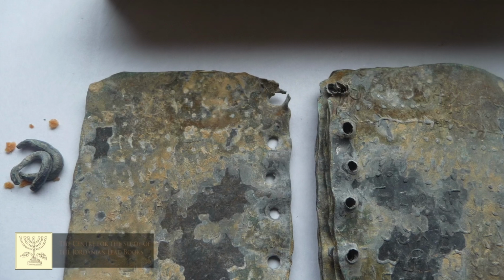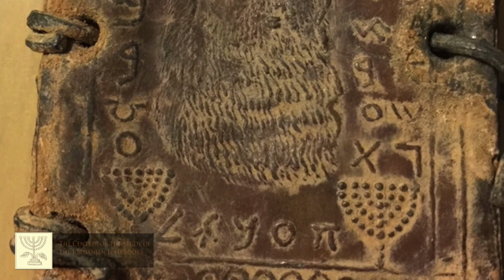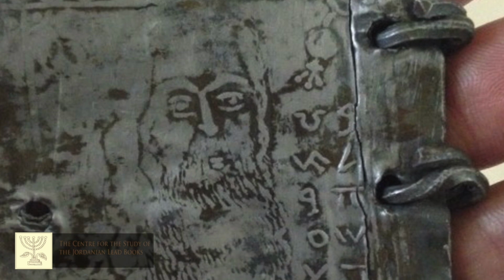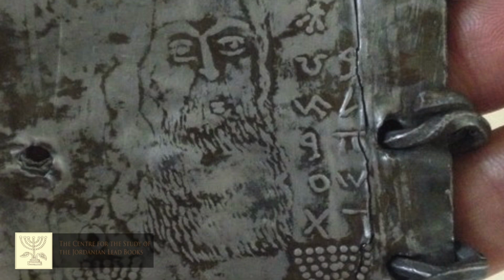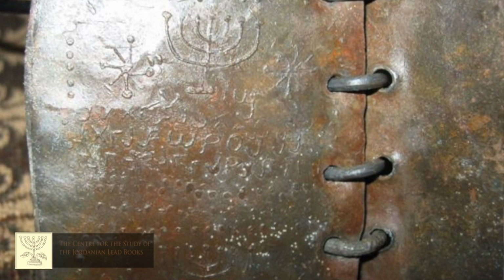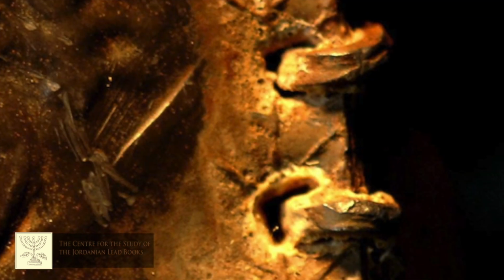The wire shows no sign of having been made in modern times either. They're uneven in shape and size and scale. They have different shapes, so they are hand hammered rather than being drawn through a round die. And you can see the cross section of the wire here, which is not at all round. And you can see that each of them has a different shape at different parts along its length. It doesn't look like modern machine drawn circular wire, which if you had bought in a batch of wire, that's what you would have. Lead isn't very good for wire, so it's difficult to buy lead wire. Definitely handmade.